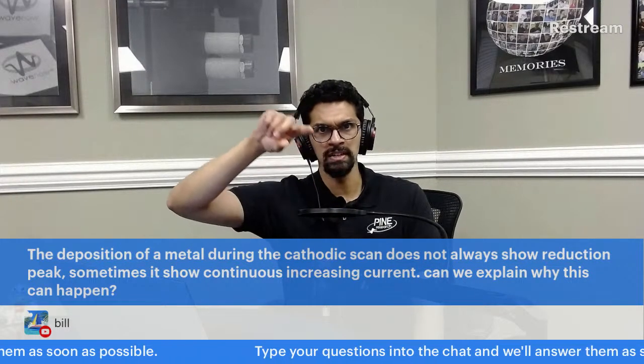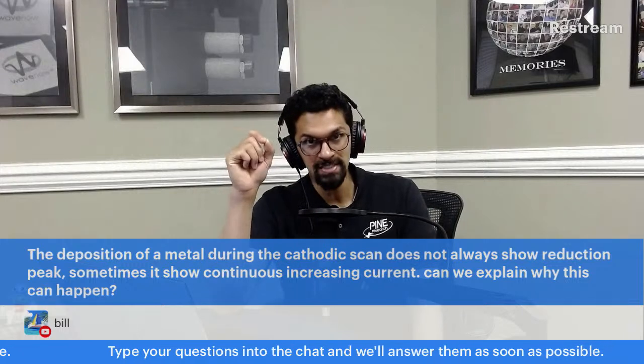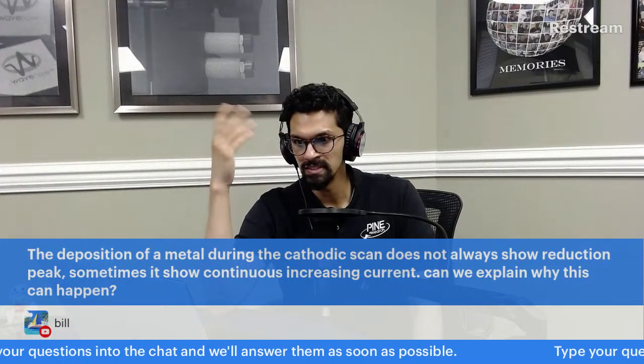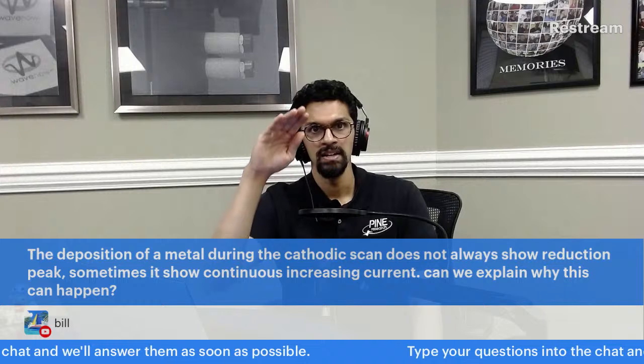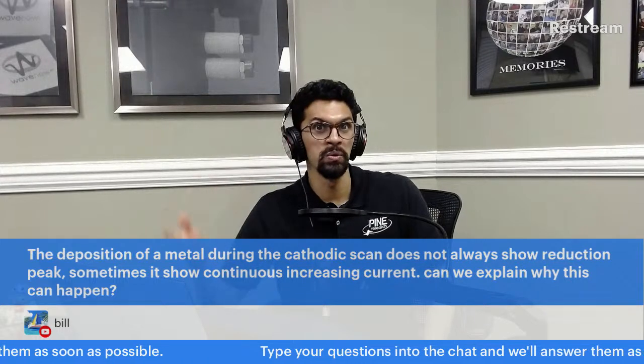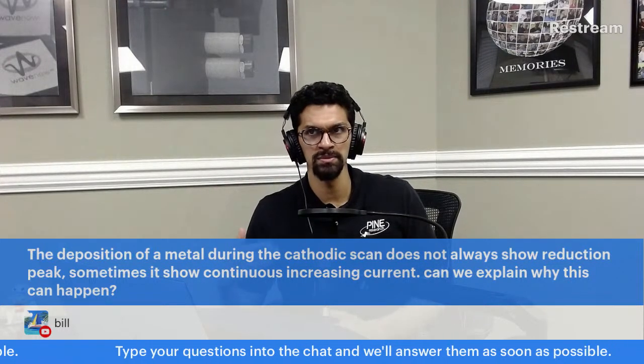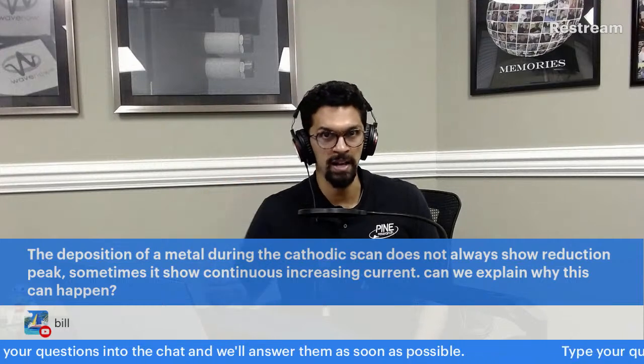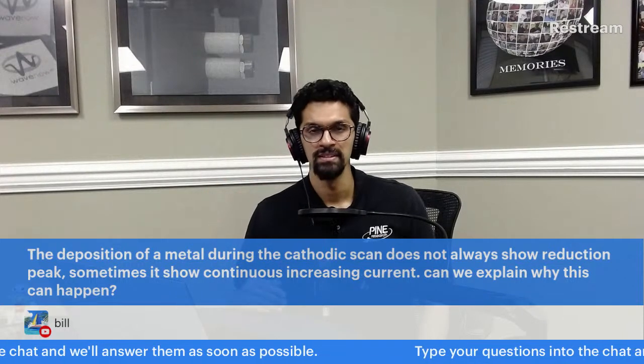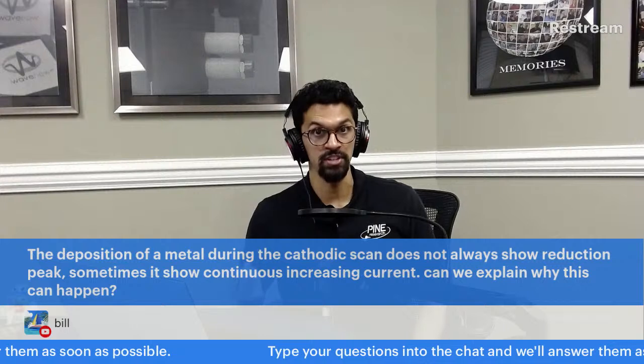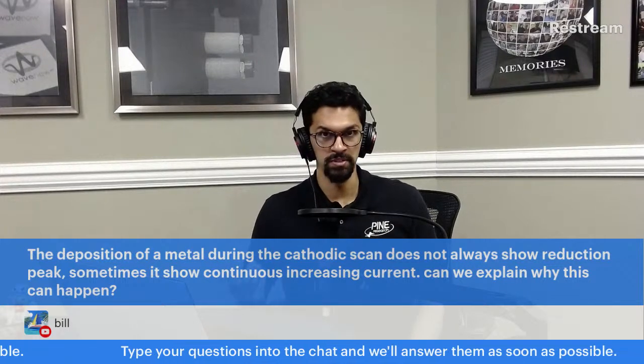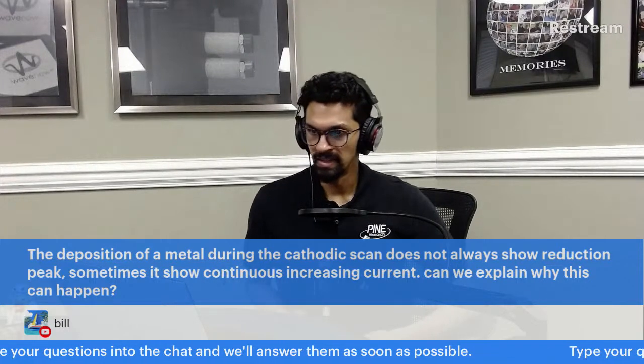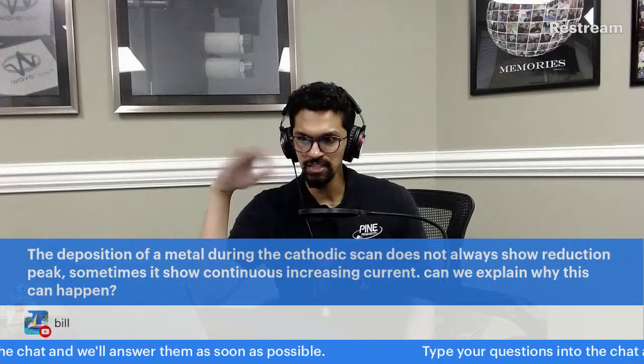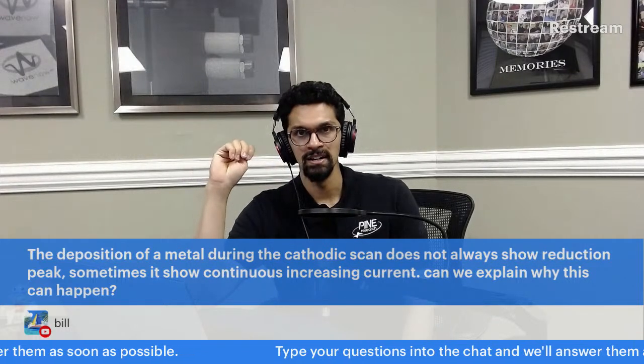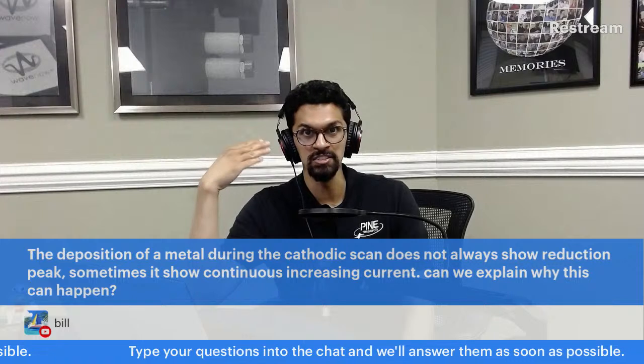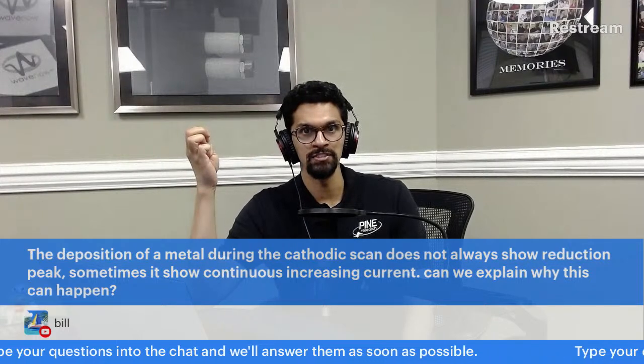So the current will increase. It reaches a maximum rate of deposition in a deposition experiment, and then it trails down. The rate at which it's depositing slows down, and this is almost always mass transport limited. So it's almost always mass transport limited, and if you see a continuously increasing current, that means it's most likely still plating.